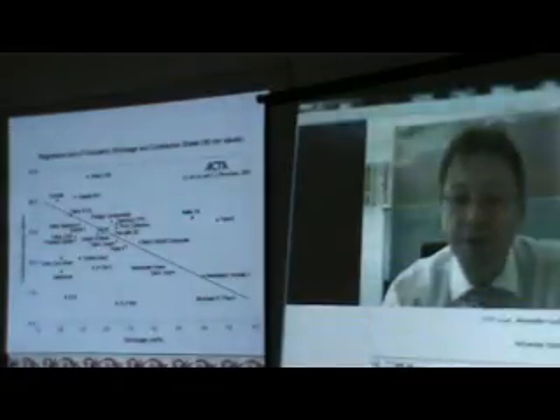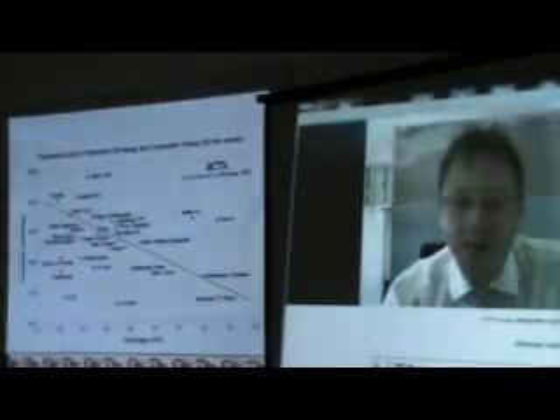When these results were first shown to many different professors, they were all very surprised because everybody expected when you have less volume shrinkage, you will have also less stress. But actually, the opposite is the case. When you reduce the volume shrinkage, in general, you have a higher stress.